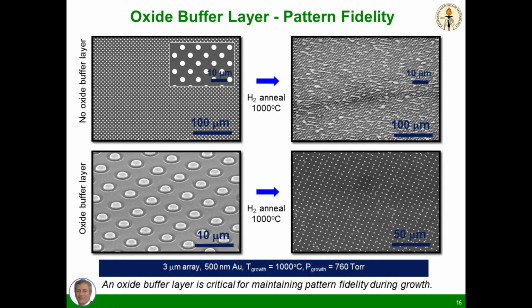If we have too much at that growing droplet, then the metal will drip down the sides like wax down a candle and will grow filaments everywhere. If we have too little metal, it'll bead up on top and will grow filaments everywhere. But if we get it just right, the metal has nowhere to go, as you can see on the right, and then we put that in our toaster oven and we grow these beautiful single crystal microwire arrays of silicon on that substrate.